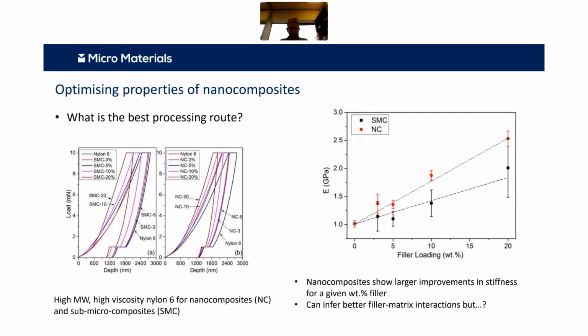thermoplastic, which has then been modified with sub-micro composites and nanocomposites, and you can see on the left they do change the curves a little bit. They change the creep resistance, they change the unloading slope, but it's not immediately obvious from those curves. It looks a bit of a mess.